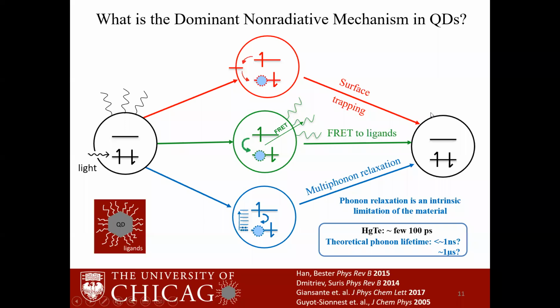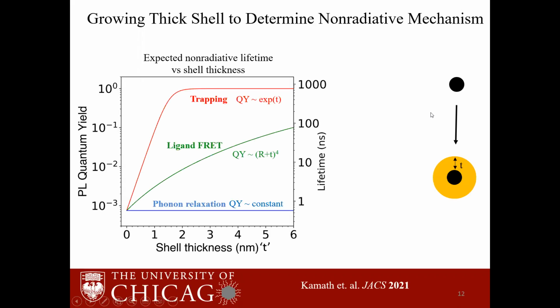we currently have. So the goal of my project is to determine what is the relaxation mechanism and find whether phonon relaxation is indeed a major limitation for the quantum dot thermal cameras. So in order to do this, we have designed the growth of a thick shell around our quantum dots. When we grow a shell, which is of a type 1 band alignment, we are isolating the electron and the hole to the core of the quantum dot and separating it from the surface.